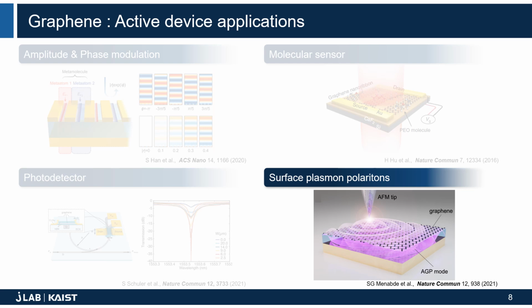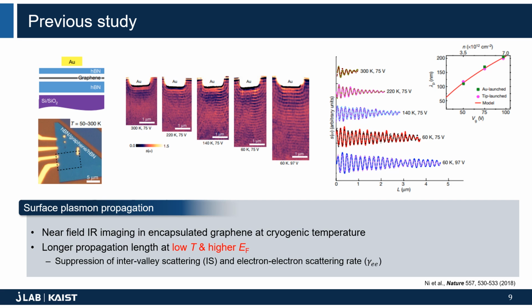Like above, despite the growing interest in graphene plasmons, most research has been performed at room temperature, and the temperature dependence of graphene plasmon properties has not been widely investigated so far. While there has been little research on the cryogenic temperature characteristics of graphene plasmons, in the paper published by the Basov group in Nature, they imaged graphene plasmons using a near-field scanning optical microscope. They observed that as the temperature decreases, the propagation length increases, which was demonstrated in the interference fringe patterns.